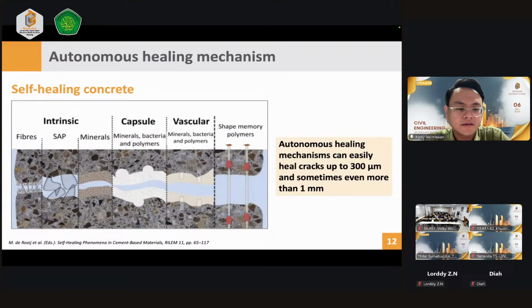For self-healing concrete, there are different pathways to achieve an autonomous healing mechanism. From the intrinsic part, we can use fibers, superabsorbent polymers, minerals. With regard to capsules, we can use minerals, bacteria, polymers. Again, we can use vascular networks and shape memory polymers. So what is the benefit of self-healing concrete? The autonomous healing mechanism can easily heal cracks up to 300 micrometers in width, and sometimes it can also heal cracks of 1 millimeter or more. This also depends on the environmental condition and the type of healing agents.